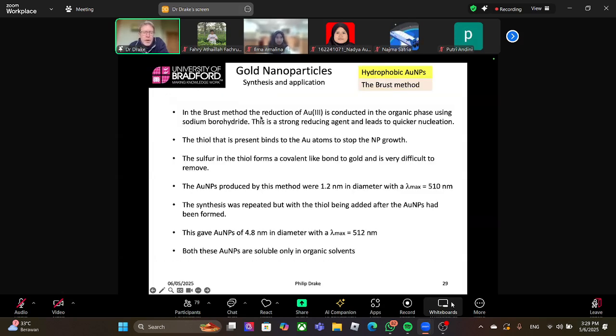So the Brust method for reduction of gold is conducted in organic phase using sodium borohydride. You add sodium borohydride as a strong reducing agent. This gives you very quick nucleation. So we have lots of nucleation sites occurring very quickly, which means we get very small nanoparticles.